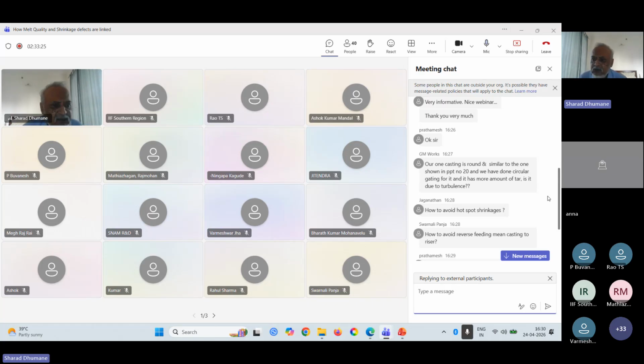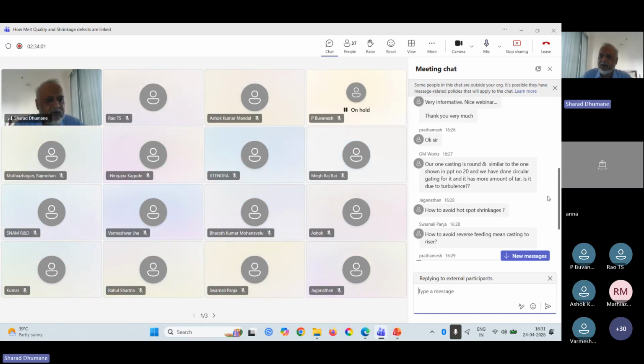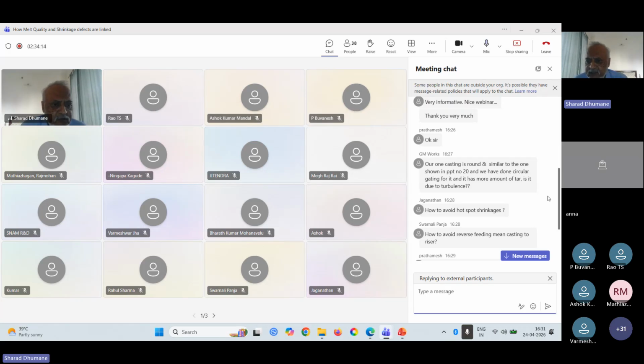Then how to avoid hotspot shrinkage. Hotspot shrinkage is avoided by giving a feeder on the hotspot. When you cover the solidification shrinkage which is happening in the hotspot, you are covering the hotspot. But in many cases, your hotspot is not really reachable by riser feeding. Recently, in the IFX also, we had taken one booth. My German principals, Visiometa, have developed a software where you can identify a hotspot in the design stage itself. When you start designing your pattern and want to see if you have a risk of a hotspot, you upload your part drawing into the software. Then it shows you where the hotspots are.